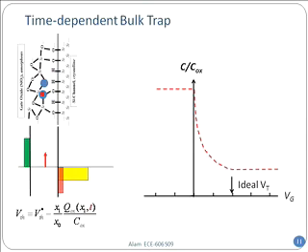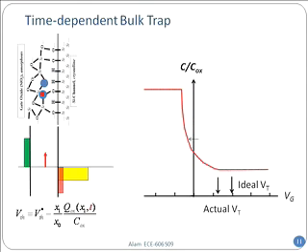You can see that Q ox at x, t is a time dependent thing, so that will change your threshold, and as a result your CV curve will shift and VT will shift, and there will be a problem in terms of drive current. So that's one problem. For thick oxide, it's a big problem. But these days, they make such good quality oxide, such fantastic oxide, that the number of these defects is minuscule, very small. However, there is another trouble.